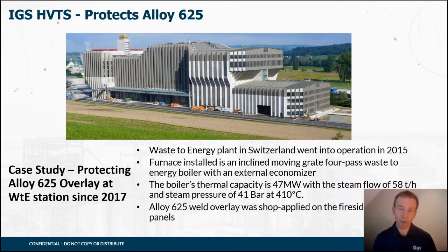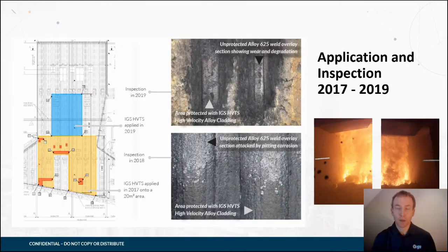So with no refractory, they installed alloy 625 shop applied cladding all the way down to the grate level inside these waste energy boilers. It started operating in 2015, but within 2 years, by 2017, they already started to see some challenges in terms of accelerated degradation of the 625 overlay. So the client undertook a study to look at what options were available, and in 2017 they decided to do initial applications using thermal spray technology in the different boilers. They had 2 lines on the plant and 4 sidewalls effectively of the boilers, so they installed thermal spray systems on each of those sidewalls in order to assess the performance.